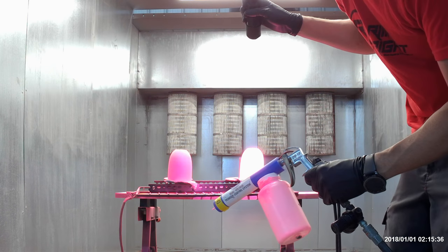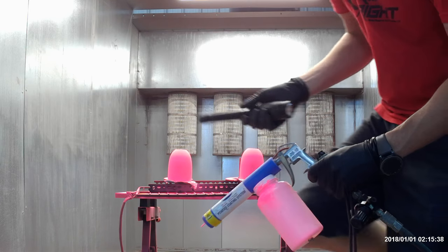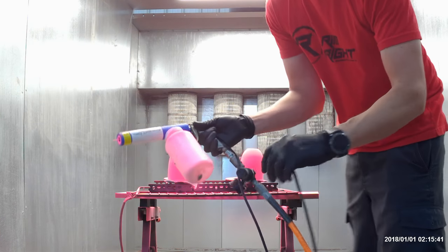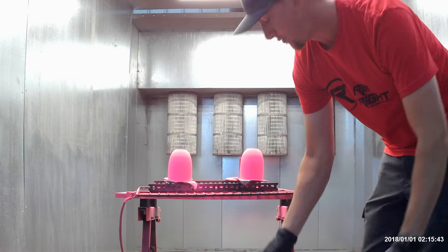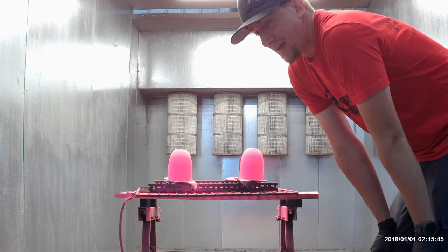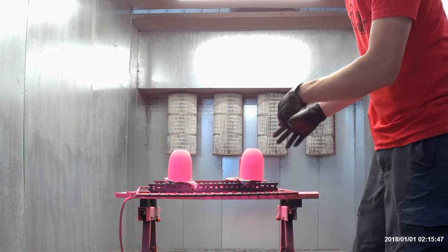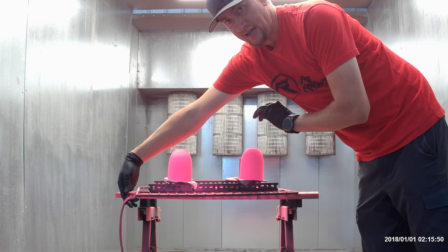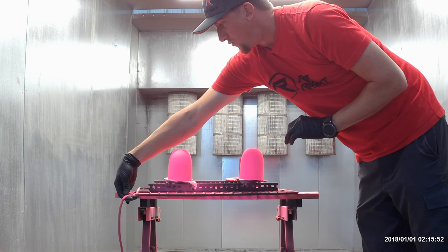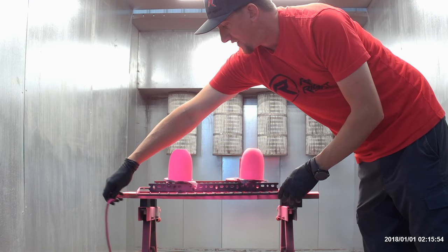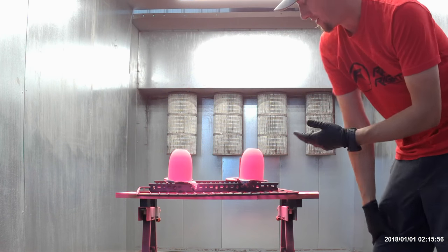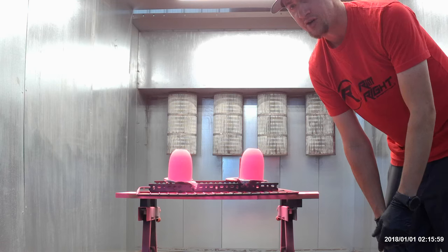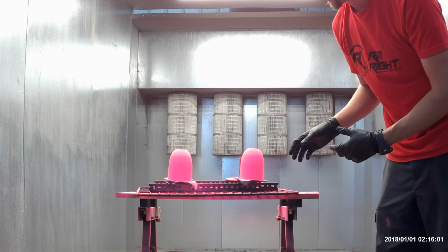Basically we'll pop these in the oven. I've got my household oven going that I showed you in a previous video. It should be up to about 400 degrees now, so we'll take this rack, we'll put it in, wait for the part to get to 400 degrees, and then we'll wait for the cure schedule, which on these is 10 minutes. So once they're in there for 10 minutes, we'll bring them out, let them cool, and show you another video of what they kind of look like and how we finish them off so that we can sell them to the customer.